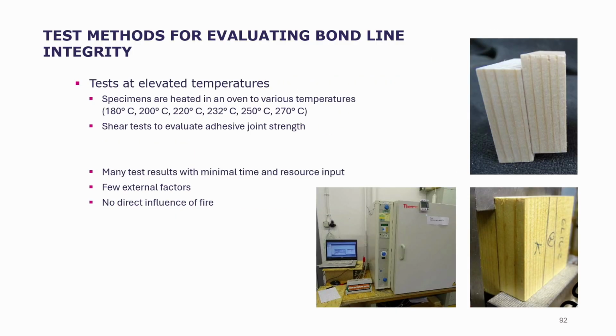There's also a third test method that has been developed in Germany by our colleagues, which are the tests at elevated temperatures. So specimens are heated in an oven up to the desired temperature, and then it's tested in shear to evaluate the joint strength. Also, we can do many tests, minimal time, minimal resources. But I would say that the positive and the negative side of this is that there's no direct influence of fire or charring. So we have plenty of test methods.